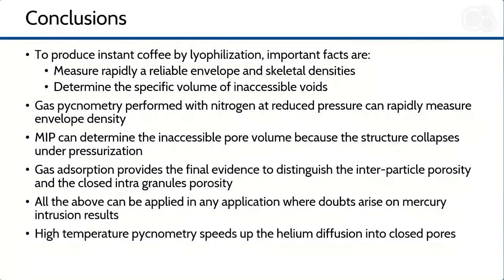All the above results are synergic and can be applied whenever it is necessary to give the right interpretation and validation of mercury intrusion results. Finally, high-temperature pycnometry speeds up the helium diffusion into the inaccessible void structure, measuring in a reasonable time the skeletal volume of the particles. Knowing the envelope and skeletal volume of the granules, the inaccessible void-specific volume can be easily calculated.